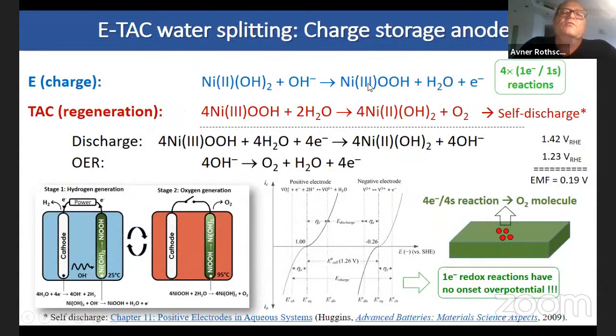By replacing this oxygen evolution reaction by the charging reaction of the electrode, we go from 4 electron per 1 site to a 1 electron per 1 site charging reaction. So basically we charge 4 nickel atoms, and then we release the oxygen from all 4 of them. The release of the oxygen is done without applying current. So therefore, the only potential that we spend is in charging reaction, and that's a 1 electron reaction that has no minimum overpotential like the OER.